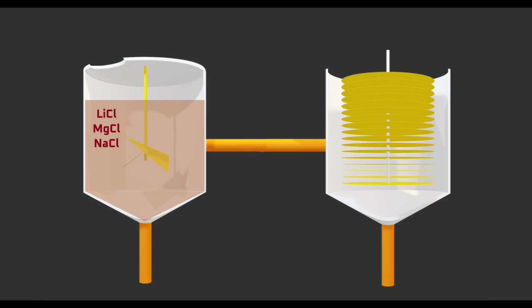I haven't seen an explanation of how the muddy water could be clarified in the flow sheets I've seen, and so I did some general chemistry research here. This turned up microfiltration, precipitation, and centrifuge processes to separate the clay from the lithium. Precipitation seems the most likely here. Clay is typically a colloid in water. Colloids are charged, extremely fine particulate that doesn't sink or settle out of solution. The charge causes the clay colloids to repel each other rather than clump together and sink.